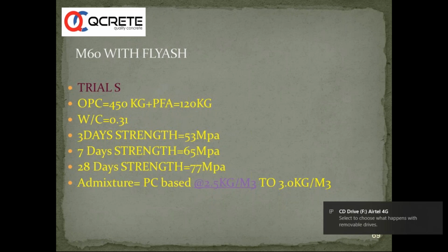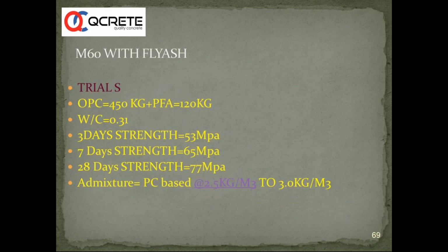So here we can see the concrete has a OPC content of 450 kgs, and fly ash is about 120 kgs. So total water cement ratio, free water cement ratio is about 0.31. You can see the 28 day strength of about 77 MPa. So almost M65 or M70 is achieved by using a proper PC based admixture.